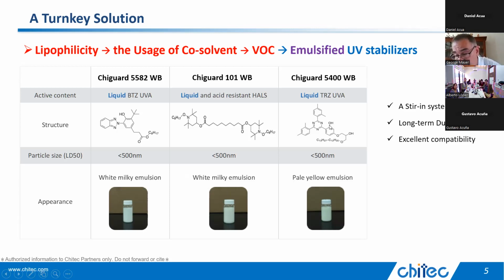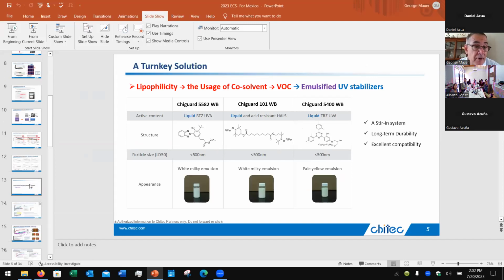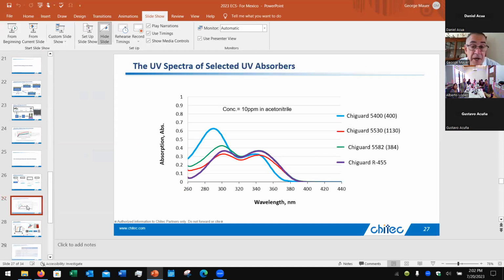The shortcoming of it is you will lose a little bit of the protection that you get from a benzotriazole out around 360, 370 nanometers, which in a lot of cases doesn't matter, but in some cases it does matter. So you would be using this blue curve of absorptivity. You'd be a little better down in the high energy part of the spectrum. You can see the 5400 is better, but out here it's not as good. So that's one of the problems if you've got those metals in there: you probably will have to give up protection out here. Does that help? Thank you.